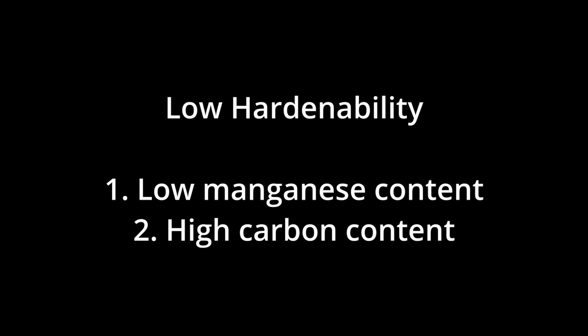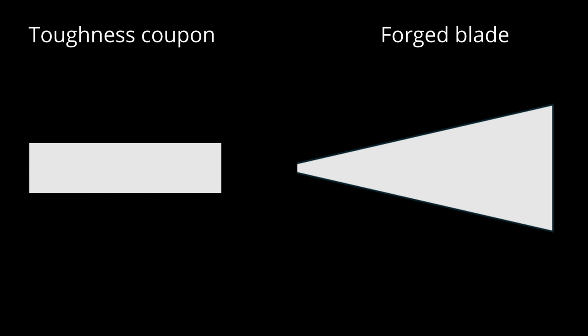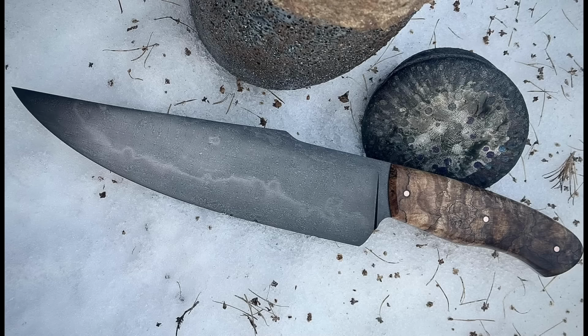Now, Spencer using 1425 for 6 minutes, it probably is working for him because he has a forged blade going into the heat treating. So it's thinner near the edge, which is the main part that needs hardened. You can see that in one of his previous blades, he has a hamon. So with a partially forged and or ground blade, you have the thinner edge, and that area is easier to harden, and the spine is thicker and will not harden as easily. And you can even add clay to slow down the cooling further at the spine. And so getting a good hamon typically indicates that you have a low hardenability steel.